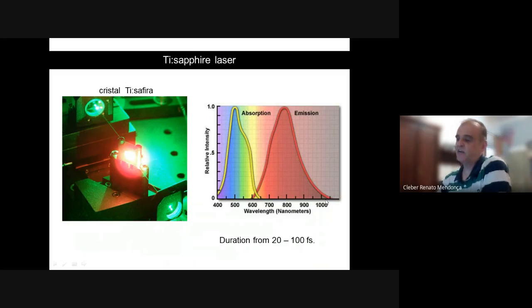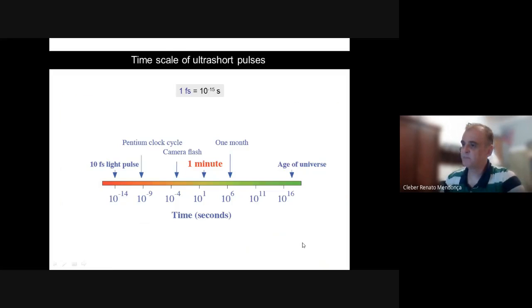The reason for that is, since we have such a broad emission spectrum, we can get a very short femtosecond pulse, as I mentioned before. Depending on the configuration of the laser, you can get pulse durations all the way from 20 to 100 femtoseconds. So how short is a femtosecond?